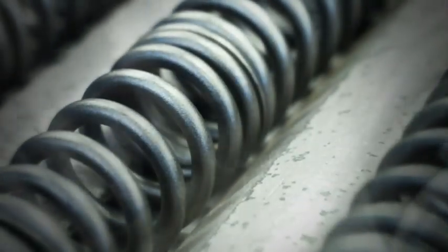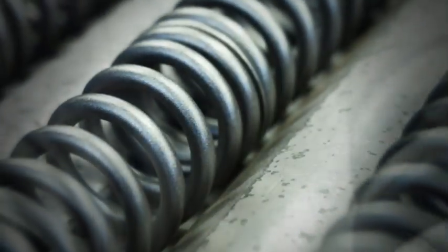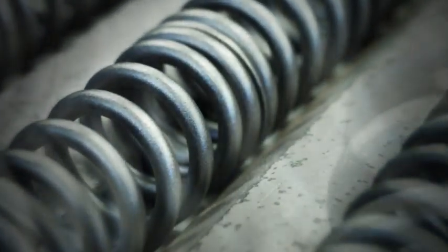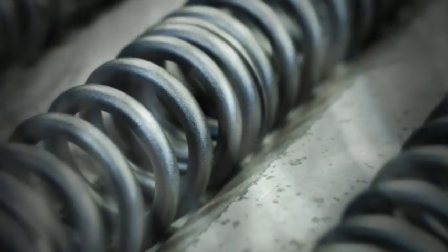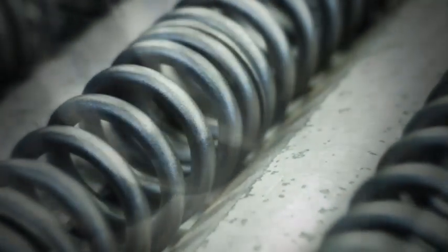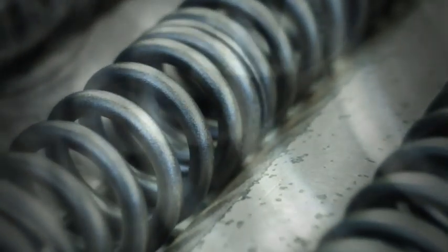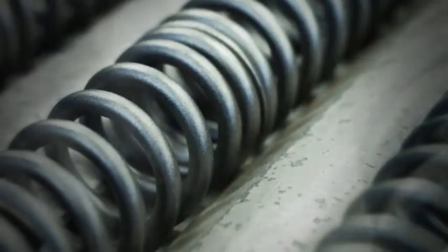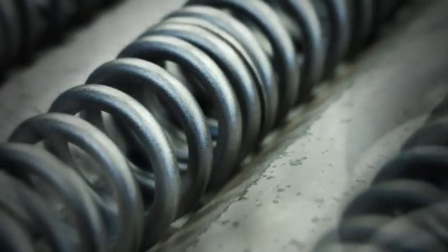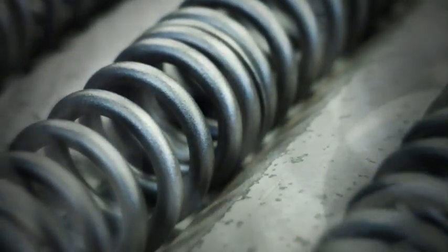One of the most important 20th century improvements in fatigue performance is shot peening. A stream of small steel, ceramic, or other controlled media strikes the spring surface. Each impact creates a tiny plastic indentation. Beneath the visible surface, the surrounding material is left with compressive residual stress. Fatigue cracks generally open under tensile stress. A compressive surface layer means the operating tensile stress must first overcome that beneficial compression before a crack can open and grow. Shot peening does not make the material invulnerable.